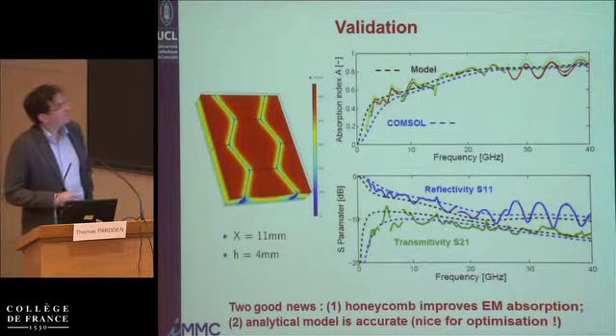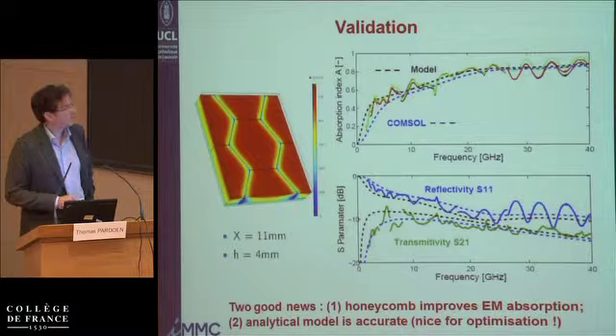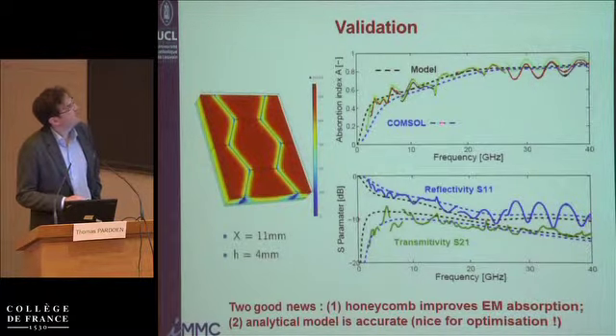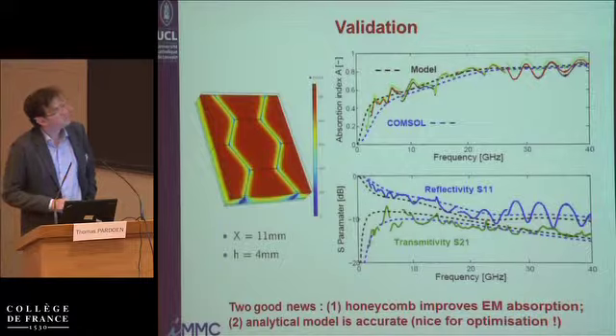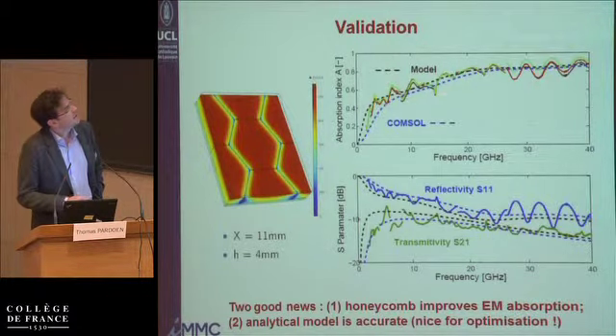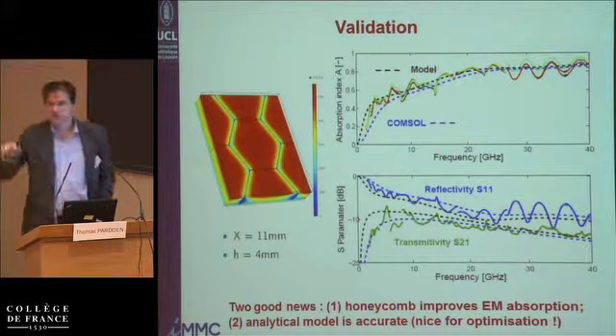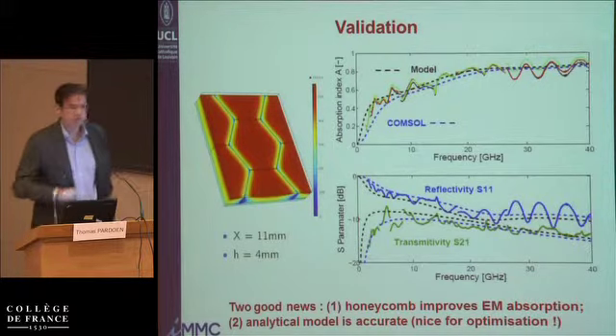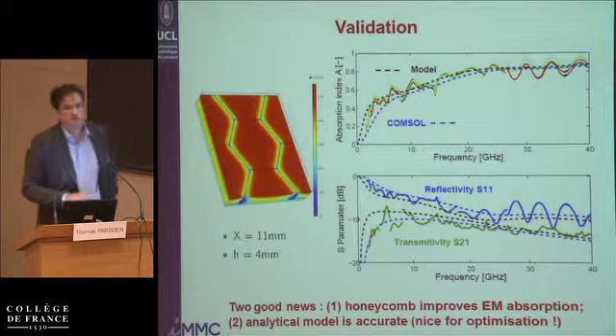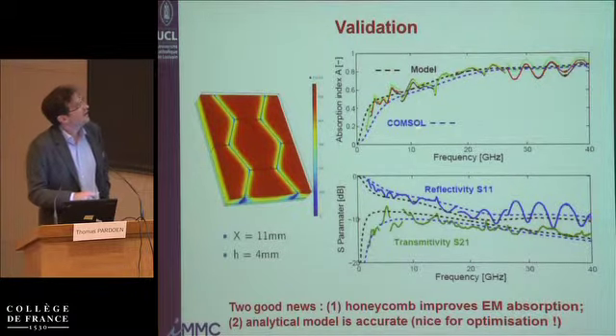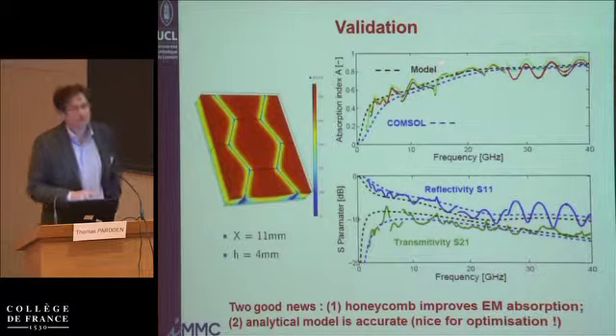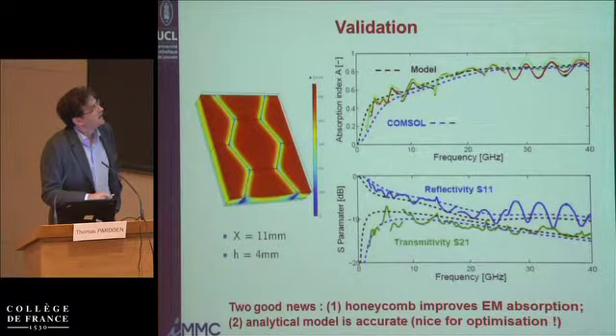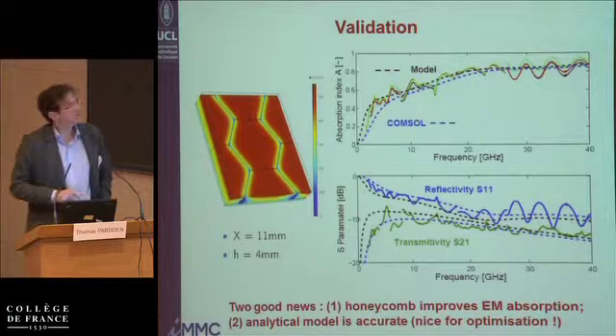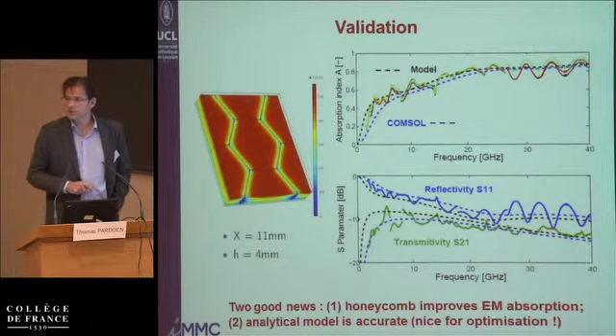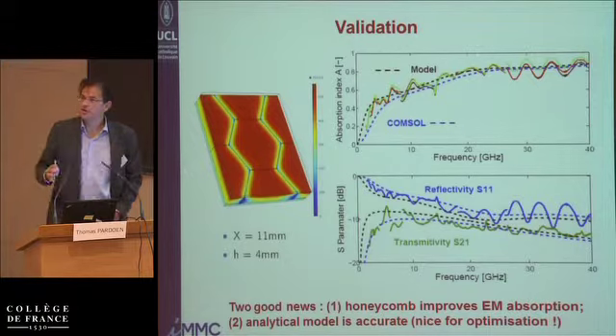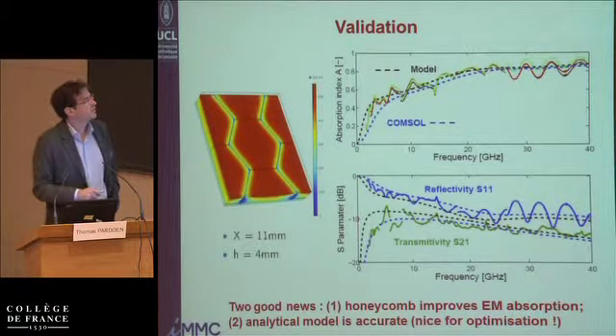So we prepared several samples, and Pierre prepared several samples of aluminum honeycomb filled with the foam. And you see the experimental results are, of course, with some scatter, and it has to do with the way the experiments are performed. It's not because Pierre is not agile enough. The model, when it's written model, it means the analytical model, and we confirmed the validity of the analytical model using finite element simulation. The good news is the analytical model, of course, can be used for optimization, which is more difficult with FE simulation.